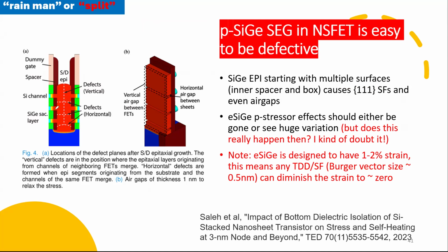It's a mixture of everything. And here it's not perfectly flat, right? It's like this. And even at the same crystal orientation, you still have the same problem, because when you grow from here, the growths are different. And eventually they will merge. When they merge, you will have defects, right?